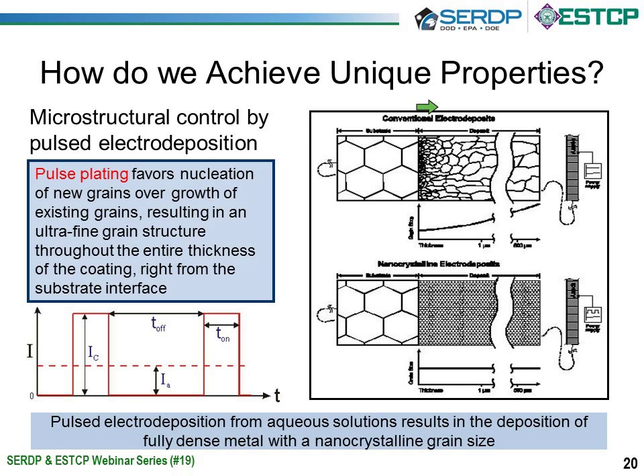So what you'll see in conventional electroplating is right at the interface of where you start plating, you might see a very fine structure, but then as you grow the thickness of the material, you'll start to see the grains elongate and get very columnar, and they'll grow to large sizes. In our nanostructured materials, by pulse plating, as well as through the chemistry of the solutions, we can control this grain size so that you can keep a very fine grain size, about in the order of 20 nanometers or so, right through the thickness. So you get very uniform properties through very large, high thicknesses.